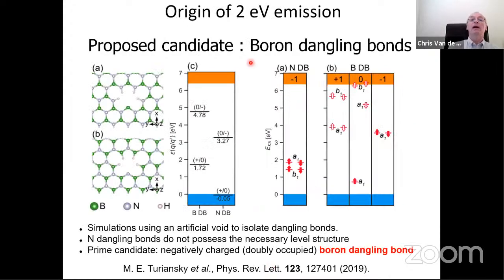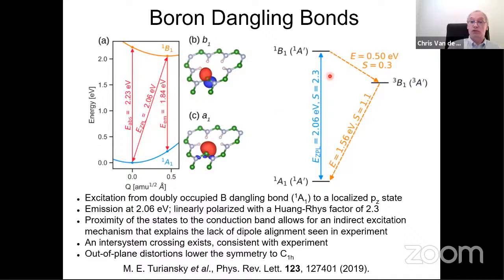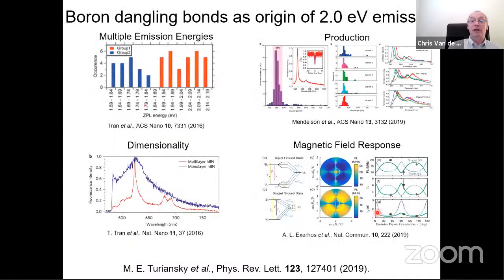For the 2 eV emission, what we're proposing is dangling bonds. Now, dangling bonds are usually considered as defects that you want to avoid. In silicon, they mess up the electronic behavior of the material. You need to passivate them, you need to suppress them. In hexagonal boron nitride, we think they are quite likely to form, for instance, near the edge of the flakes that are usually studied experimentally. And if we study their optical properties, they are very close to all the properties that are observed experimentally for the 2 eV emitters. Okay, and again, we use configuration coordinate diagrams, we analyze radiative and non-radiative rates, and it's all extremely close to the experimental observations.